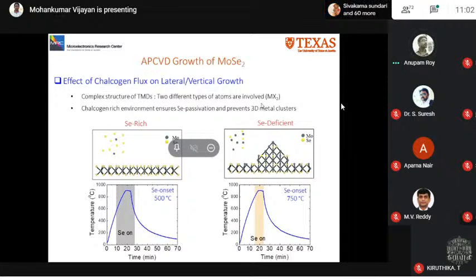So the transition metal atoms are much heavier than the chalcogen atoms. Thus, their diffusion on the surface is very different. To compensate for this, the ratio of chalcogen to metal should be tuned in such a way that there are always enough chalcogen atoms to passivate the incoming moly atoms. This can be achieved by controlling the chalcogen environment, which in the CVD experiment we achieve by changing the selenium onset temperature. So for example, on the left side, when we want to achieve selenium rich condition, we have the selenium onset temperature at 500 degrees C. On the right side, when we want to achieve selenium deficient condition, we have the selenium onset temperature at 750 degrees C.